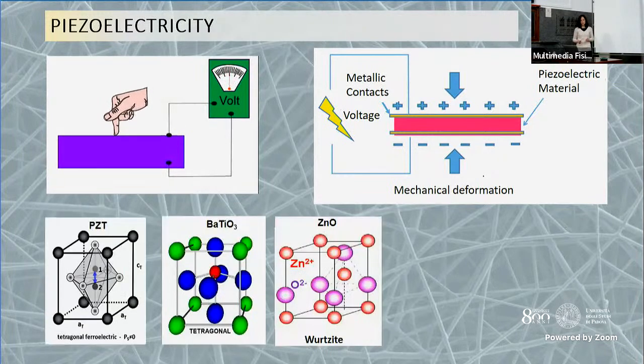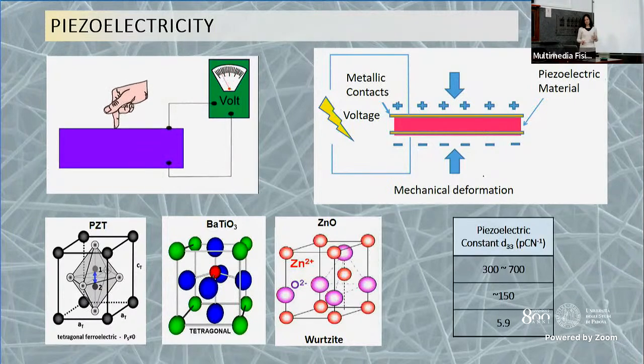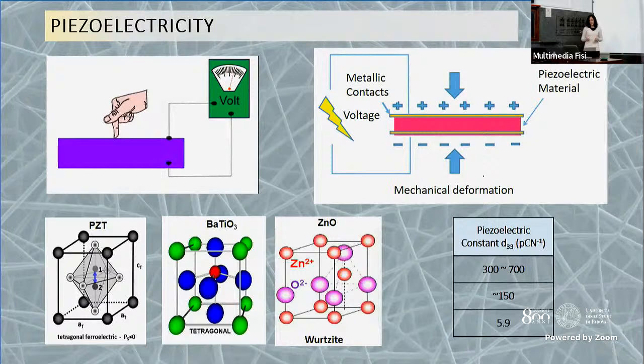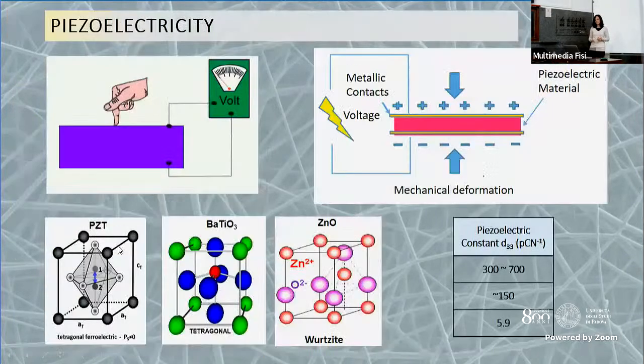The most used piezoelectric materials are inorganic. Here are some representative examples. As you can see, they are crystalline materials. In particular, they are characterized by a non-centrosymmetric structure. In most cases, they are tetragonal. And of course, they are characterized by a high piezoelectric constant. In particular, the perovskite PZT is the most used piezoelectric one. However, it is based on lead. And as you know, there are several concerns about the use of lead for commercial purposes and devices, so it is something that needs to be avoided.